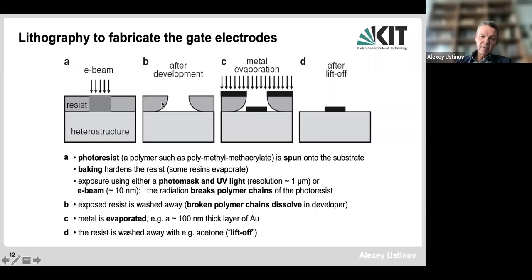And basically here you have a line which forms a kind of gap between two pieces of polymer, which can be as small as the width of your electron beam. And typically in electron lithography, lines of the order of, let's say, 20 nanometers are possible. Then you evaporate metal from top, and then you put everything in acetone, and you remove this resist and the resist on the other side, together with the metallic layer on top. And what you are left with will be a very narrow metallic electrode.